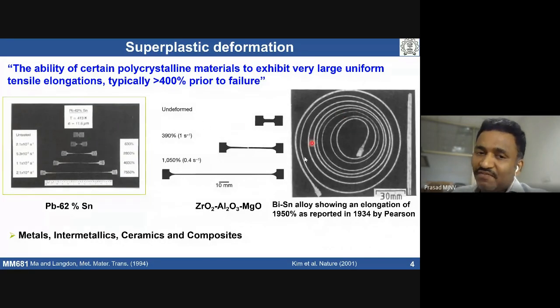People have observed this kind of phenomenon in various classes of materials: metallic materials, intermetallics, ceramics, and composites. For example, here, lead tin alloy, lead with 62% tin, which is a popular solder alloy. This group, Ma and Langdon, demonstrated that if this alloy is deformed at a temperature around 413 Kelvin with a grain size around 10 micrometers, at different strain rates, then at a particular strain rate of 2 times 10 to the minus 4 per second, the specimen showed 7,550% elongation. This is the record, the largest elongation reported in any class of materials, in lead tin alloy.